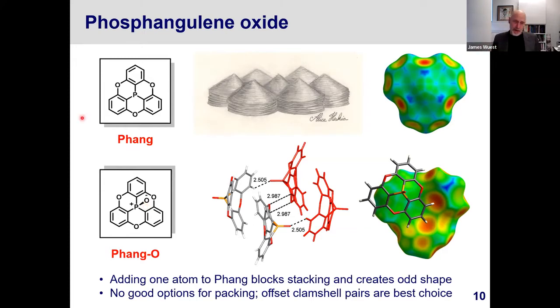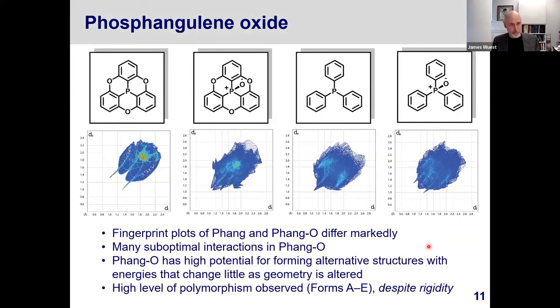And the answer is that these compounds form what I will describe as a sort of an offset clamshell pair that's illustrated by the two phosphangulene molecules shown here in red. They can't stack anymore. And the best they can do is form this type of pair in which you have CH-pi interactions that are mutual and help hold this clamshell pair together. So I've illustrated that with this Hirshfeld surface that lets you see a little bit more clearly what the interactions are. It's basically an unhappy molecule from the perspective of packing in a periodic structure. And I would say that this is basically the best that it can do.